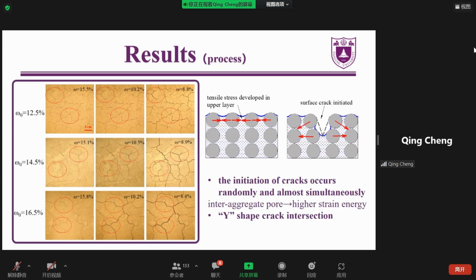For the soils with aggregate structure, the macropores between the aggregates have a larger pore size, leading to a higher strain energy prior to cracking. Thus, the places between the aggregates can be regarded as surface weak zones, resulting in the crack initiation. Moreover, we can find from the pictures several crack initiation points appearing almost simultaneously.